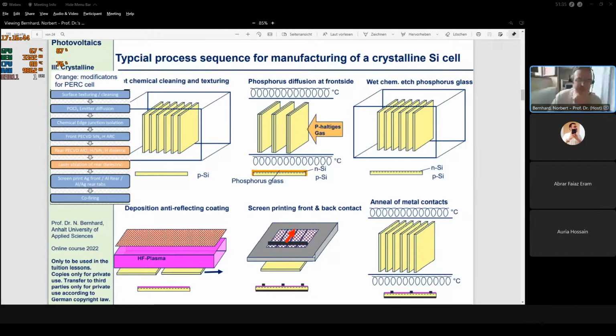Okay, the next step is the deposition of the anti-reflective coating, which at the same time is a passivation layer. That means a layer which reduces the recombination centers at the surface. At any semiconductor surface, we find a lot of defects, and a big percentage of these defects act as recombination centers, just reducing the lifetime and thus the diffusion length of the charge carriers. And therefore, we need this passivation layer, which is usually done in a plasma deposition process. That means we have here a high frequency plasma, and in this high frequency plasma, the chemical radicals are created which trigger the deposition process of this silicon nitride layer here.